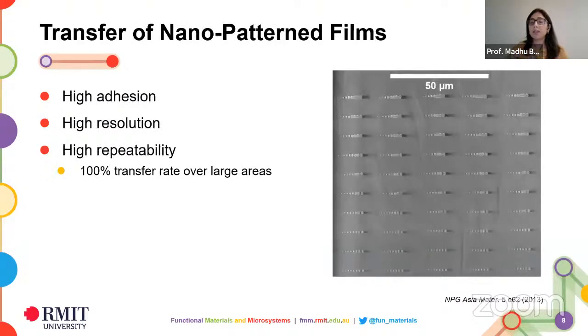Now, you can either microfabricate these or you can nanofabricate these. So you don't have to only stick to photolithography. What you see over here are very high resolution patterns which have been nanofabricated using an electron beam lithography system. So no matter whether you use nanostructures or microstructures, the same transfer process can be used to effectively transfer oxide films onto a silicone rubber platform.